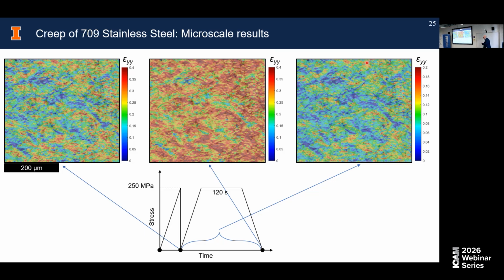To investigate that, we devised this protocol. We do not have identical microstructures that we can test again and again, and once you test it plastically, that's it. So essentially what we did here is the following. We did one plastic cycle. This is just stress, and this is above the yield stress, at 650 degrees C. So we did one cycle of plastic loading, followed by one creep loading cycle at the same stress level with a certain dwell time. Maybe we played with the dwell times and other things, but I won't go into those details.